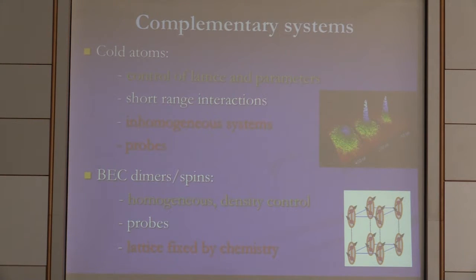And if J is 100 times larger, you cannot control anything with magnetic field because you would need to apply a magnetic field of 200 or 300 Tesla. So you need to find materials which are in the perfect range for what you want. Fortunately, chemists made fantastic realizations in that. But of course, it doesn't replace the flexibility to be able to assemble by hand spins and atoms the way one would like.